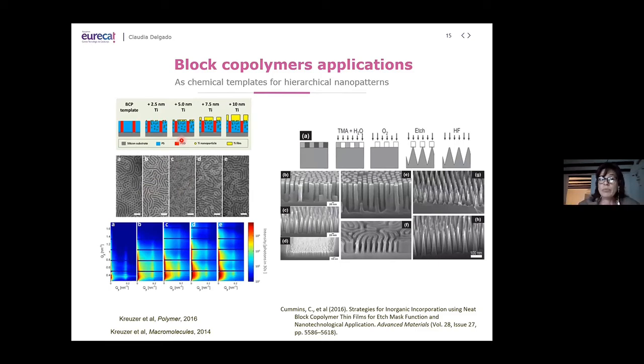In this case, the periodicity, so the distance between lines, is 20 nanometers, so it's really small, and it's just printing and annealing, everything at room temperature. In this case we evaporated, but it also works with infiltration methods of metal nanoparticles, and they also end up in ultra-thin metal layer templating. Here is the application that we pursued for high chemical contrast etching masks made in a low-cost, large area way.